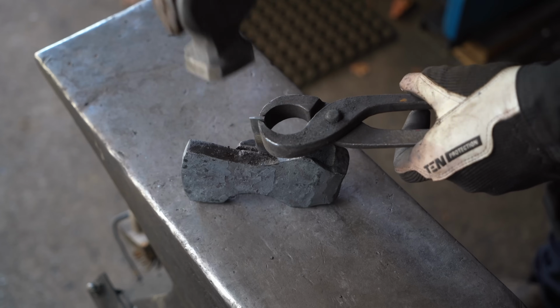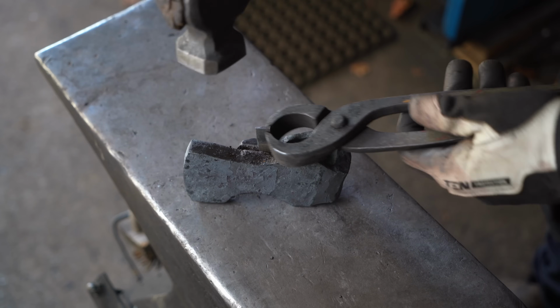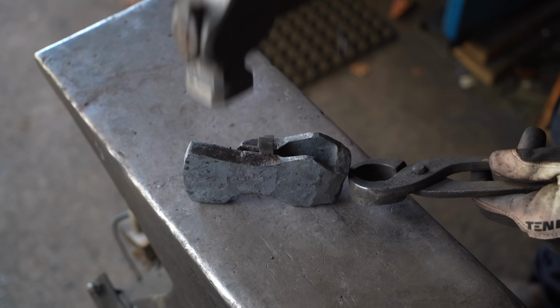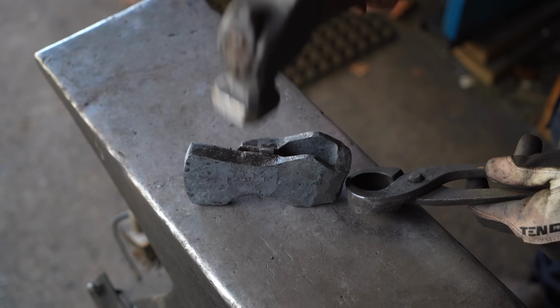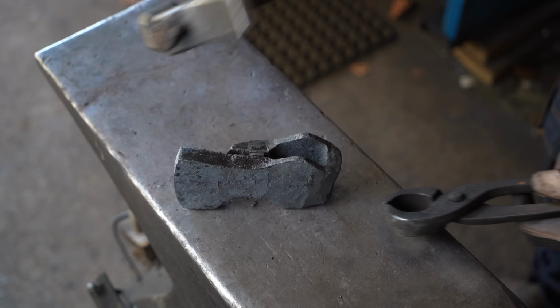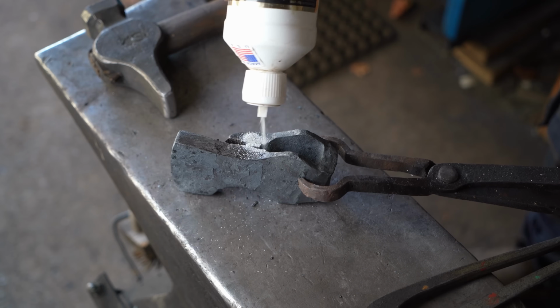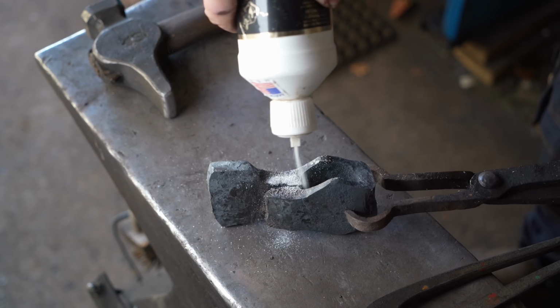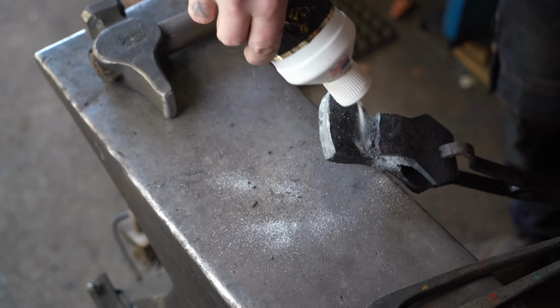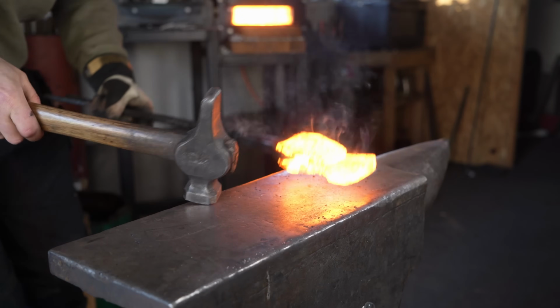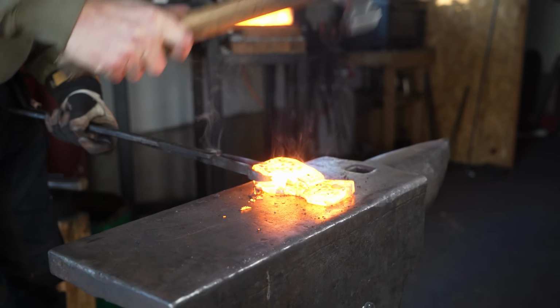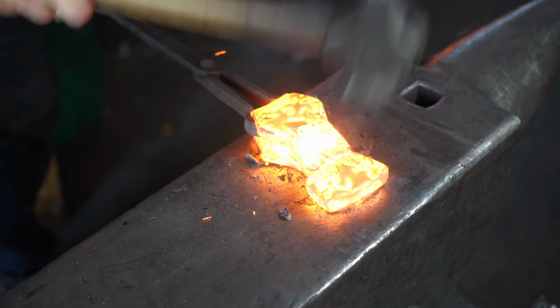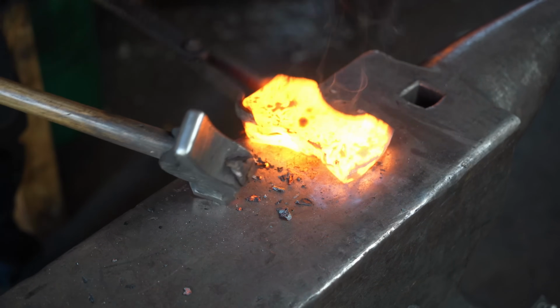I then insert a small piece of high carbon steel just in front of the eye. Since high carbon steel generally has a lower welding temperature than mild steel, it helps making a stronger and more secure weld, in my opinion. I then apply some flux and heat it up to a bright yellow color and then begin forge welding. I repeat this process a few times until I'm sure that it's welded.